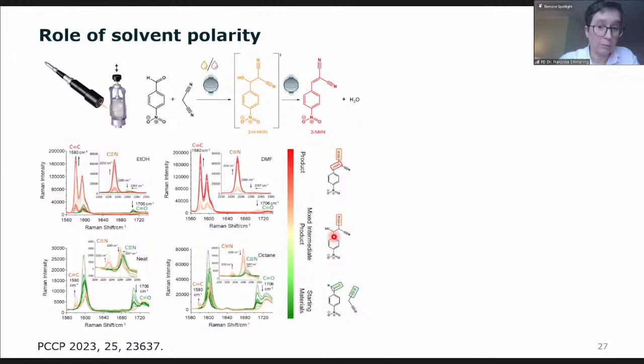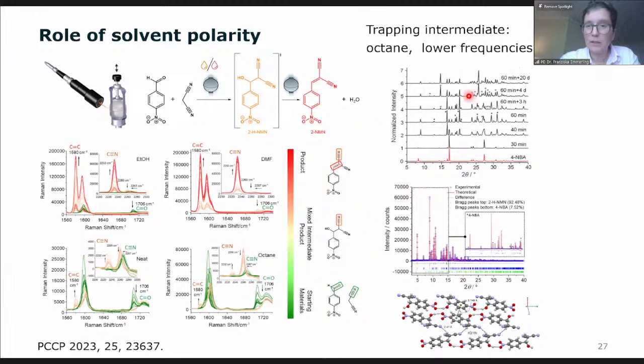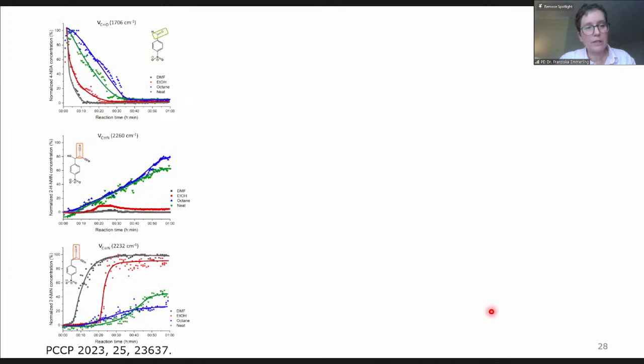So we then tried to trap this intermediate, and this is possible if you know the process, then you can stop at a certain time and try to isolate it. And that is what we have done here. You see after 60 minutes, we have the more or less pure intermediate. And then you can solve the crystal structure from powder data and assign this crystal structure. And then we tried to understand how these reactions proceed. We could monitor that using Raman spectroscopy, looking at the different bands. Here you see the CO stretching band, which vanishes during the process. It takes more time for the neat grinding conditions, and also using the nonpolar solvent. And you can see here with DMF, the process is rather fast.